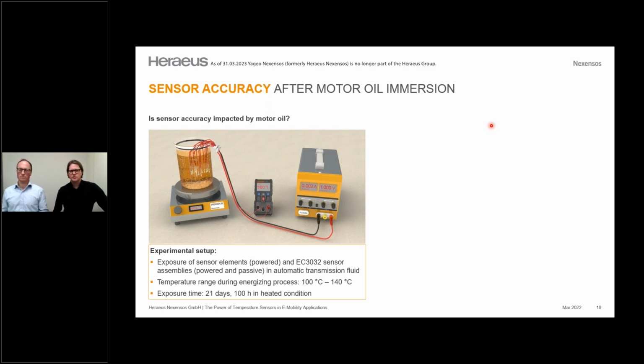And to come to an answer whether we are oil resistant or not, we do a very simple test, as you can see here in that picture. We took a lot of these sensors into a pot of automatic transmission fluid, which we heat up in a range of 100 up to 140 degrees, and we have an exposure time of 21 days.